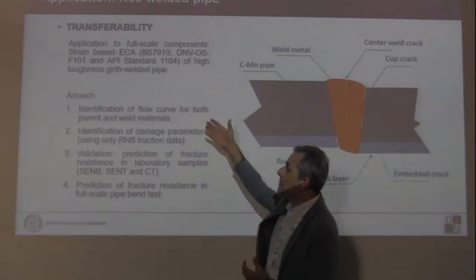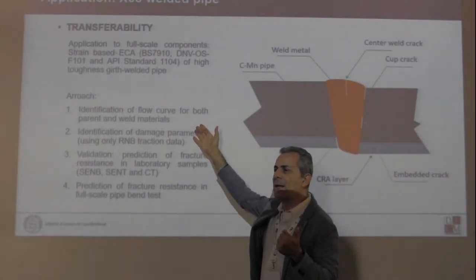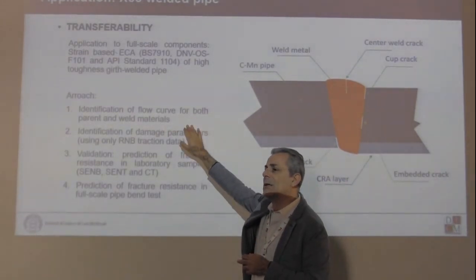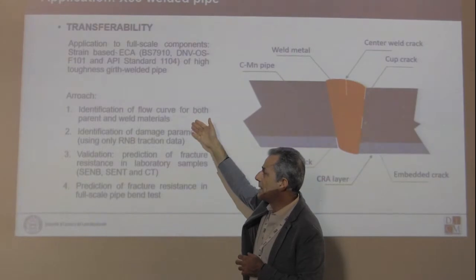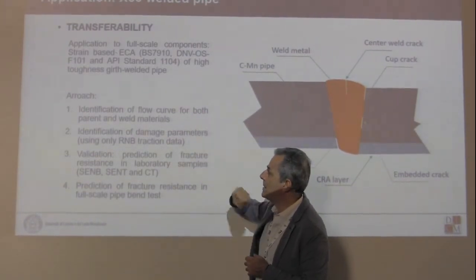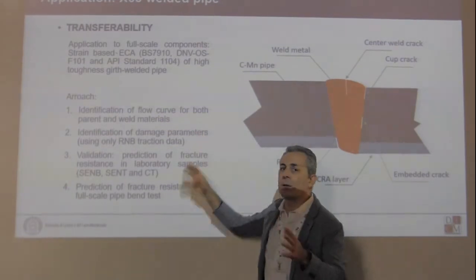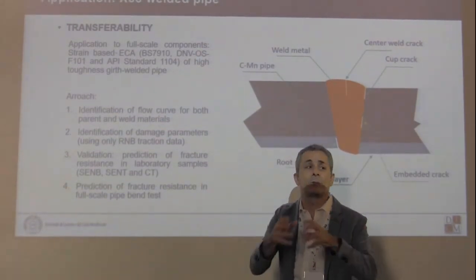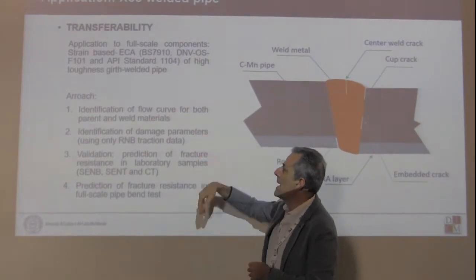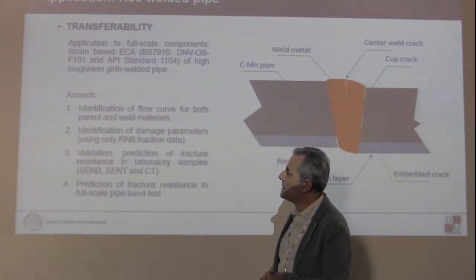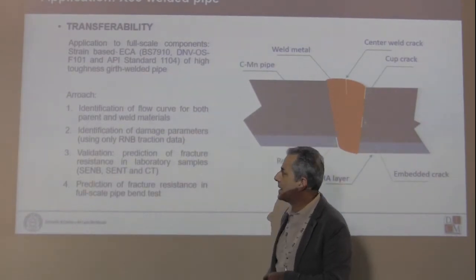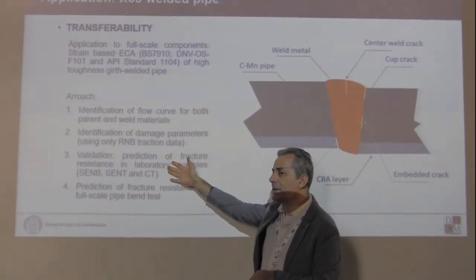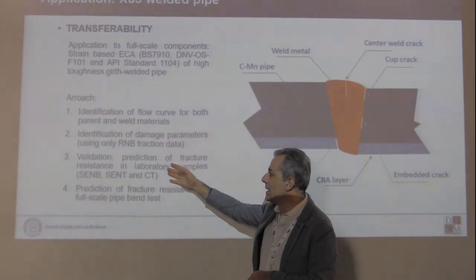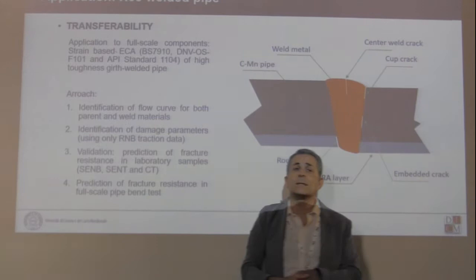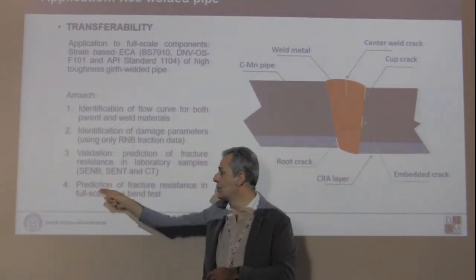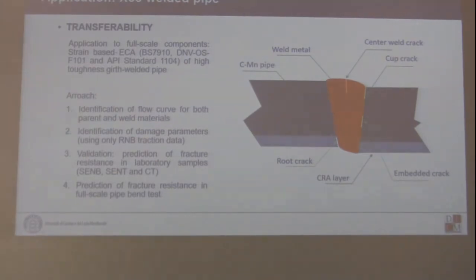This approach relies on the fact that you have to identify firstly the flow curves of your material, and this is not tricky because this is dedicated to computational simulation. So we provide a procedure how to do this for the parent and weld materials. They identify the damage model parameters, performing very simple tests at the industrial level, that is traction tests on round notch bars, and identified by retrofitting these failure data with finite element to generate the damage model parameters, validate these model parameters in predicting the fracture resistance in laboratory samples, and then use the model to predict fracture resistance in real life, in full-scale tests.